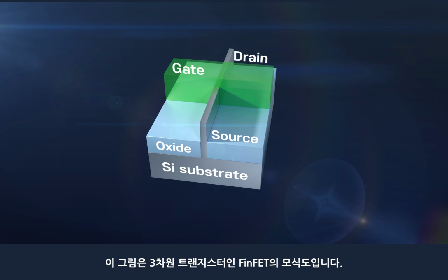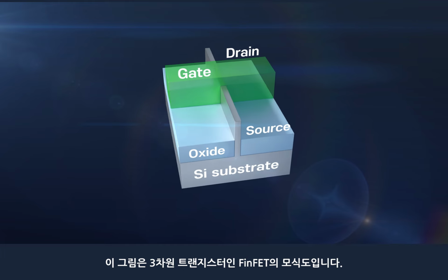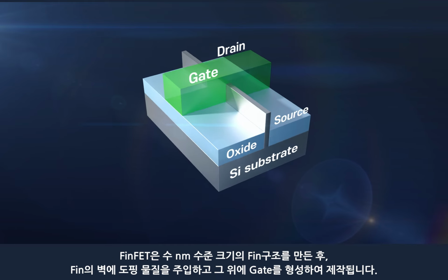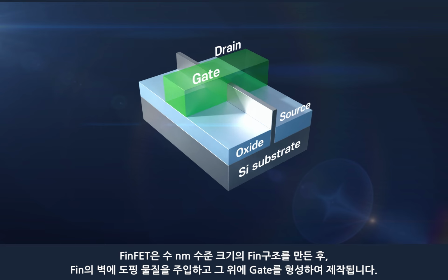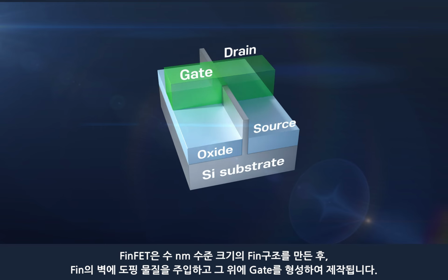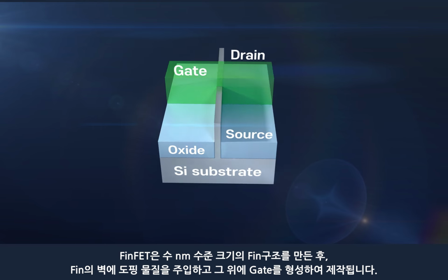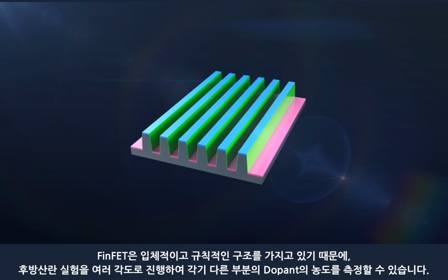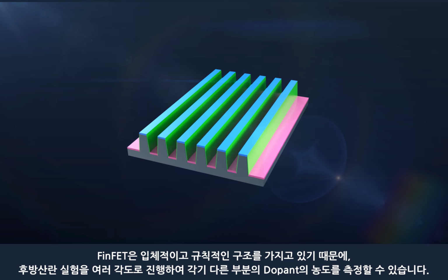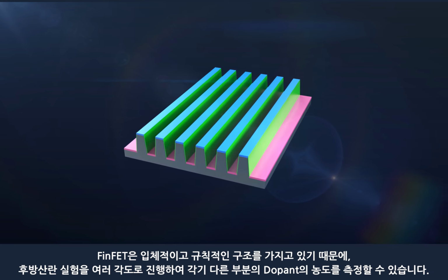This figure shows a schematic of a FinFET, a 3-dimensional transistor. FinFETs are fabricated by building a fin structure with a size of several nanometers, implanting dopants into the walls of the fin, and then forming a gate on it. Because FinFETs have a 3-dimensional and regular geometry, the concentration of dopants in different regions can be measured using backscattering experiments performed in multiple directions.